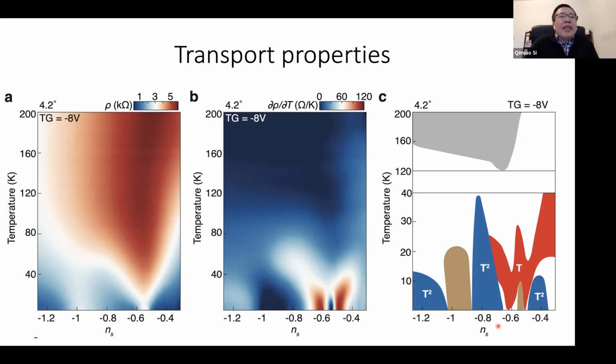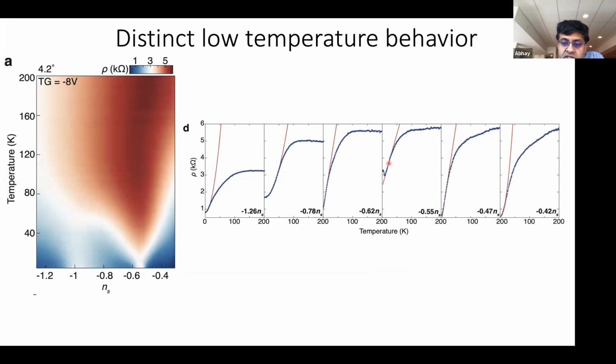In the half-filled case, resistivity versus temperature doesn't say anything about whether there is a phase transition or not. It does. At exactly half filling, you'll see the resistance versus temperature suddenly start to rise below the phase transition temperature. So that could also not just be the metal insulator transition, but also some sort of magnetic ordering. In principle, that's a possibility. We believe that, within mean field theory, that's an antiferromagnetic insulator. Whether it's simultaneous or not is a tricky question, but it's possible that it signifies some magnetic ordering transition as well.